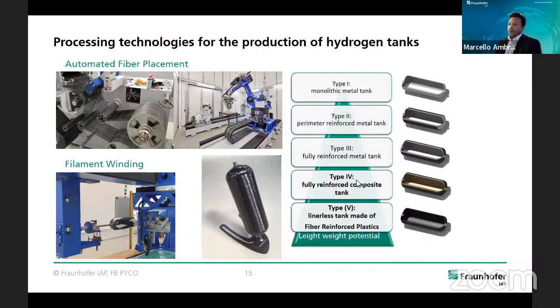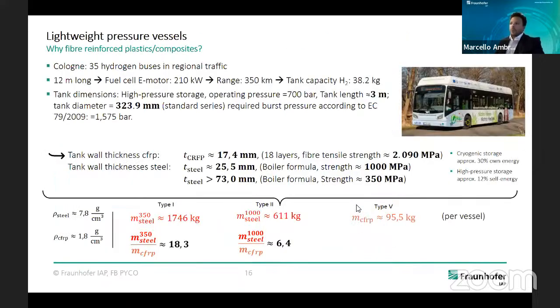The type 4 pressure vessel is pretty much the same as the type 3. The only difference is that we have a polymer liner inside instead of a metal liner, and type 5 is a linerless tank made fully of fiber reinforced plastics. So as you can see here, we have a high lightweight potential at type 5, and this is what I'm gonna explain to you now based on an example for hydrogen buses.